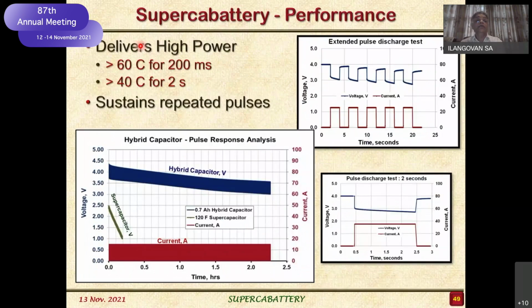And if you see power wise, 60 C rate for pulses of 200 milliseconds is there. For more than 2 seconds, about 40 C it is able to sustain. Then over nearly about 800 pulses. If you see current wise, the red one is able to go for almost more than 2 hours and 15 minutes. We could get continuously pulses of about 60 C or 40 C. We are getting it. So this is how we were achieving.